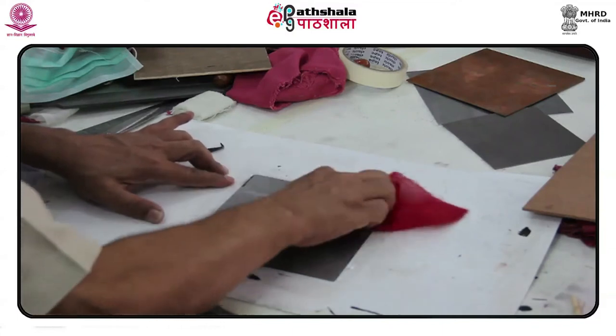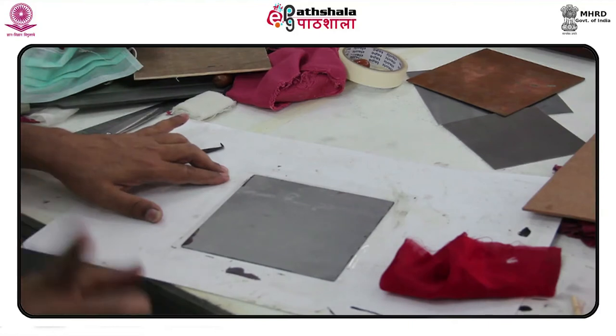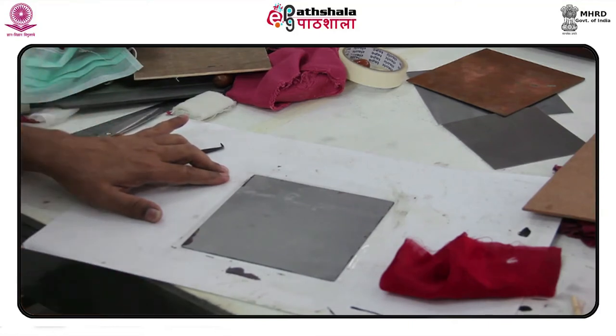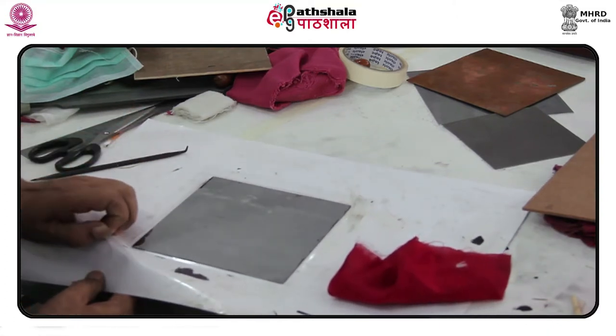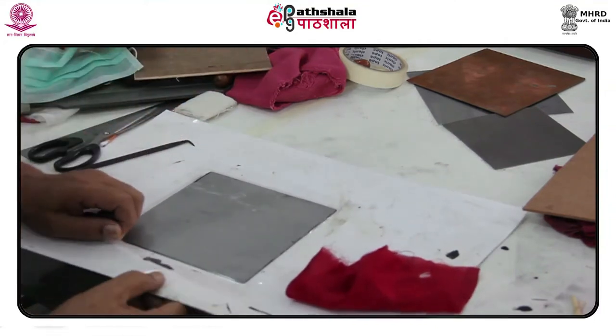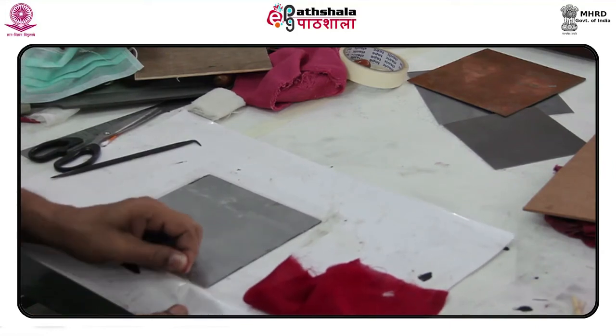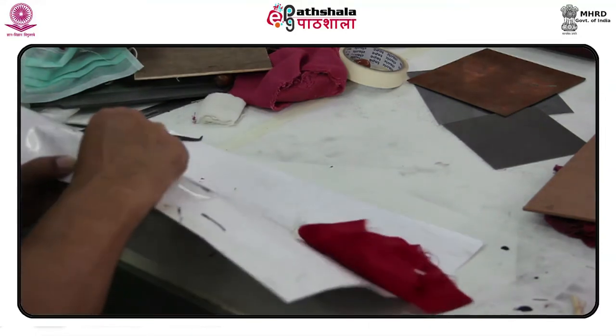After backing, the plate may need to be stopped out on the front again. The etching is done with nitric acid, and it removes more material than a line etch. Timing for a soft ground etch is generally no more than 45 minutes before the ground gives up. Crater-like biting can happen beyond 45 minutes, so it needs careful watching. Mineral spirits are used as solvents for soft grounds; a rosin-based alcohol stop-out varnish works best on soft ground as it doesn't break the ground.